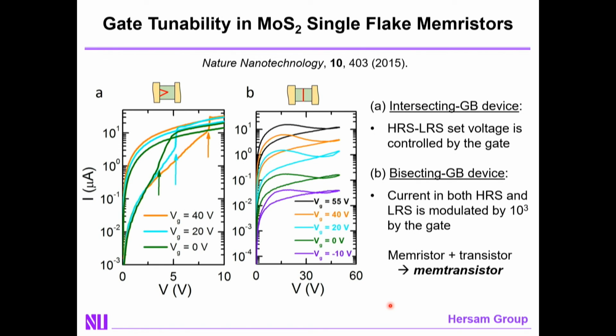Okay, so what? Well, memristors are not new. They've been around for at least a decade or so. So why would I want to do this in MoS2? Well, the reason is that molybdenum sulfide is low-dimensional, and as a result, you can gate the response, which means that you can now utilize the gate potential to tune the details of your memristive response. And depending upon the geometry of the grain boundaries with respect to the channel, you can either use the gate to tune the trip voltage between the high and low resistance states, or to tune the overall conductance of the device, in this case, tuning it by many orders of magnitude.